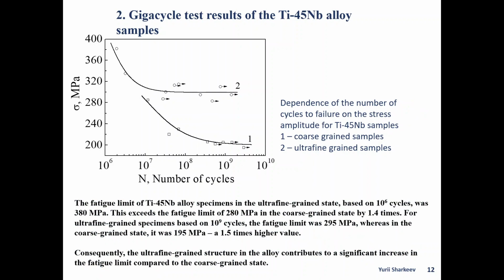The fatigue limit of titanium niobium alloy specimen in ultrafine grain state, based on 10 to the power 6 cycles, was 380 megapascals. This exceeds the fatigue limit of 280 megapascals in the coarse grain state by 1.4 times. For ultrafine grain specimens based on 10 to the power 9 cycles, the fatigue limit was 295 megapascals, whereas in the coarse grain state it was 195 megapascals, a 1.5 times higher value. Consequently, the ultrafine grain structure in the alloy contributes to a significant increase in the fatigue limit compared to the coarse grain state.